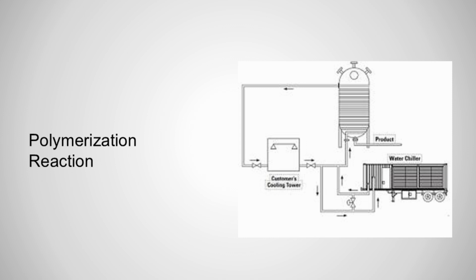This reaction is highly exothermic, generates heat, so cooling jackets around the reactor strictly regulate the temperature, typically kept cold around 5 degrees Celsius for high quality rubber or hot around 50 degrees Celsius depending on the grade.